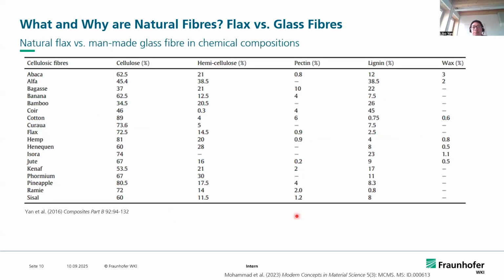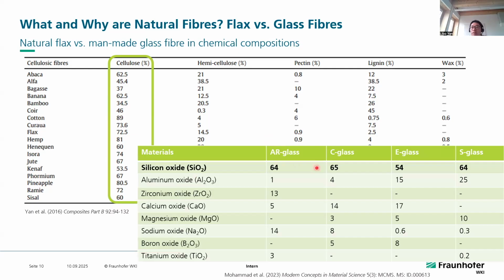Let's move on to the comparison between the flax fiber and the glass fiber. In this table, I gave the chemical compositions of those widely used plant-based natural fibers. As you can see, different plant-based natural fibers have different chemical compositions, like cellulose, hemicellulose, pectins, and lignins in different quantities. So this diversity gives individual fibers completely different mechanical performance and durability. By contrast, the glass fibers have a stable chemical consistency, mainly dominated by silicon, around 54% to 65%, with other different oxides to change the function.